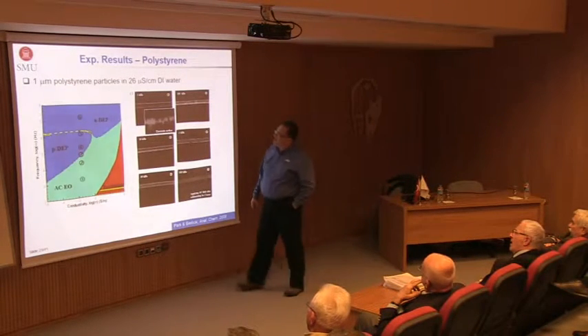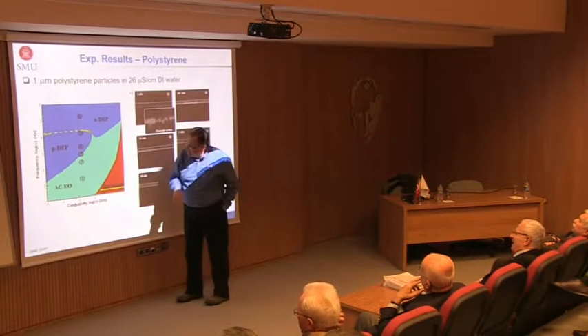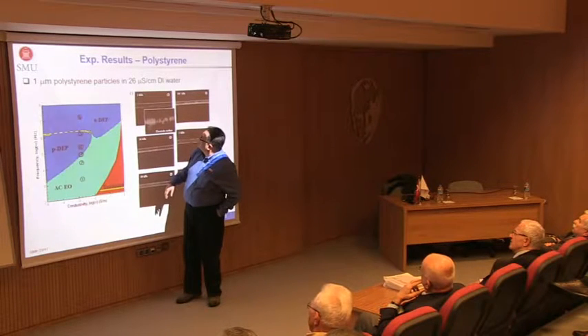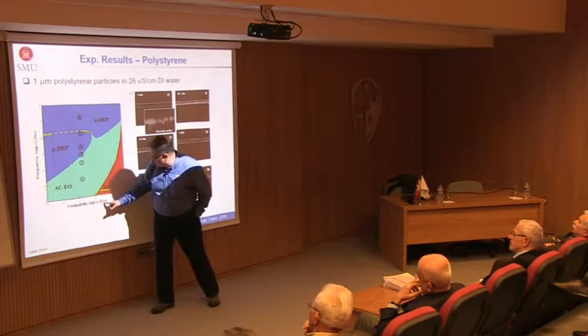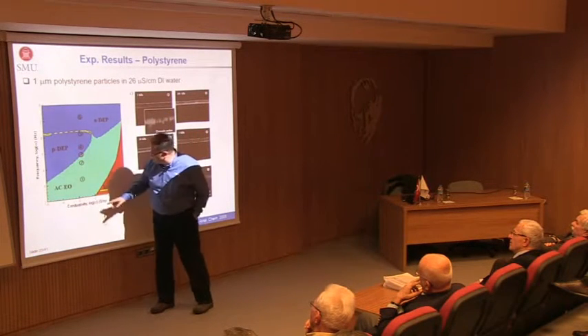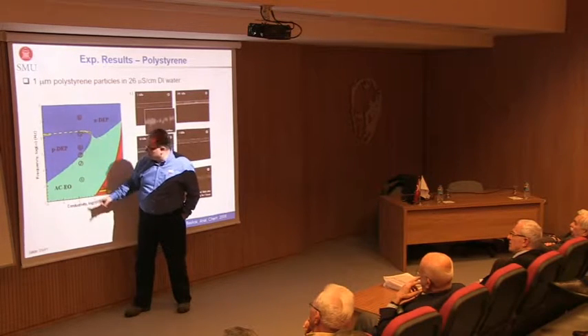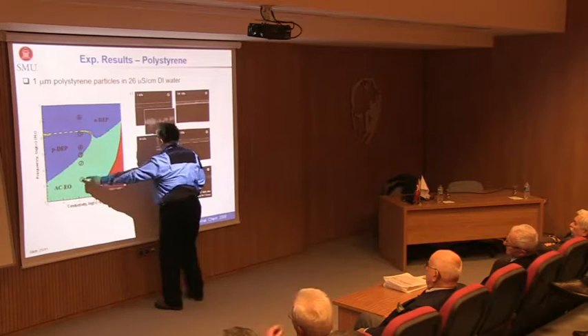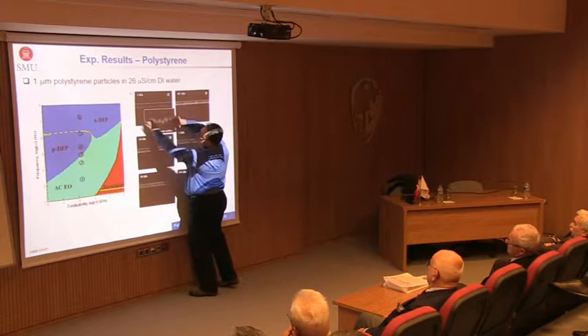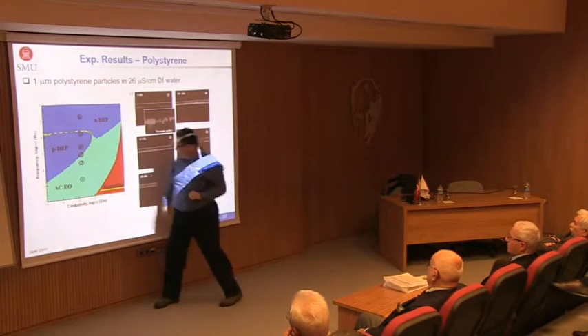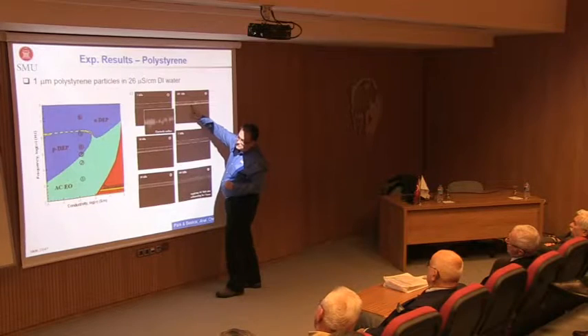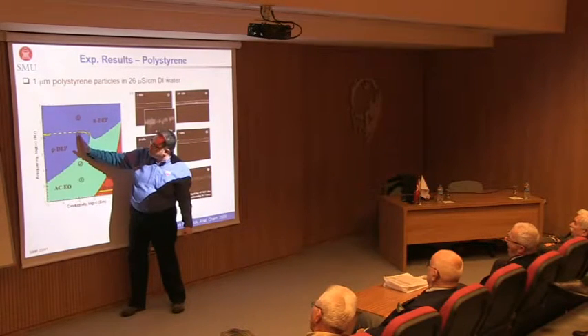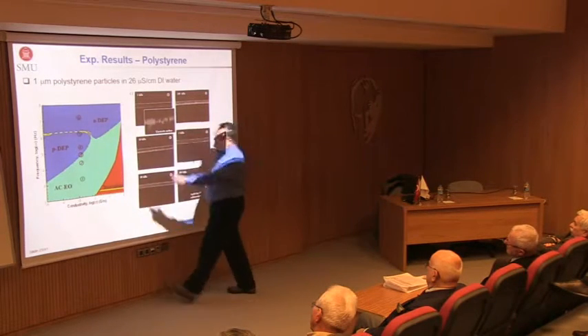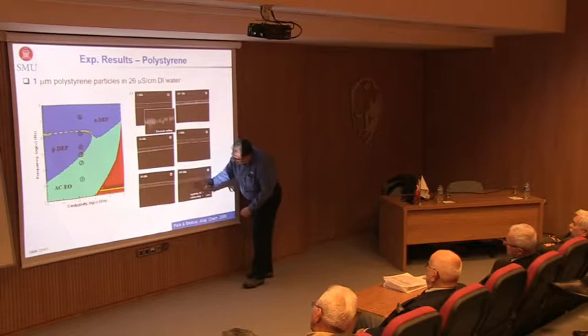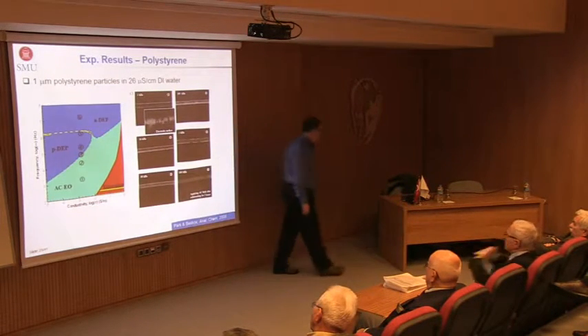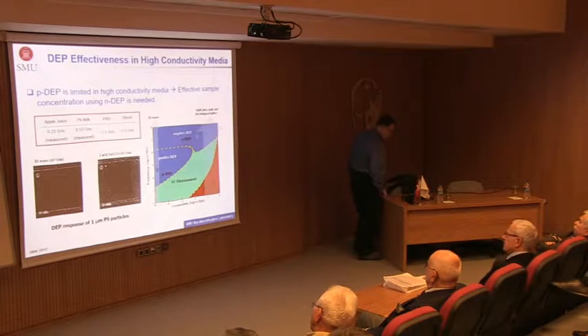And this is for polystyrene particles in DI water. And what will happen here is that actually this is not really Siemens per meter. Probably there's a mistake. This may not be the correct conductivity. But we use this following conductivity. And as you can see, this is 0.1. AC electroosmosis, yes, the particles are mostly on the top of the electrodes. As you get like 0.4 here, which is up there, you have a strong positive DEP. You get closer, and now positive DEP is turning into negative DEP, so it gets weaker. And over here is a negative DEP. That means the particles are pushed away. So we basically, in this paper, validated this phase diagram for various cases.